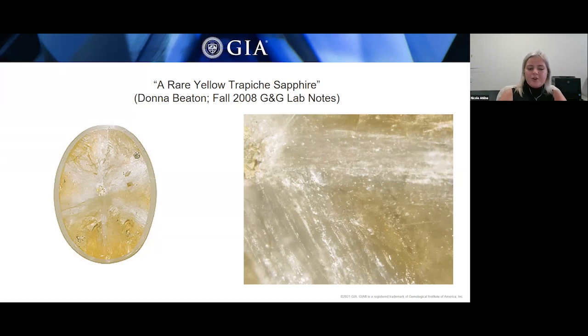And so the triangular growth sectors had a yellow body color, and they had inclusions such as fingerprints, two-phase inclusions, and reflective thin films. But the reflective thin films that were seen in the white spokes were parallel to that center core. So both the triangular sections and the white spokes were very different. That difference in inclusions and color suggests that the sapphire crystallized from the core outwards, with the sectors and the arms growing concurrently, but at different rates.